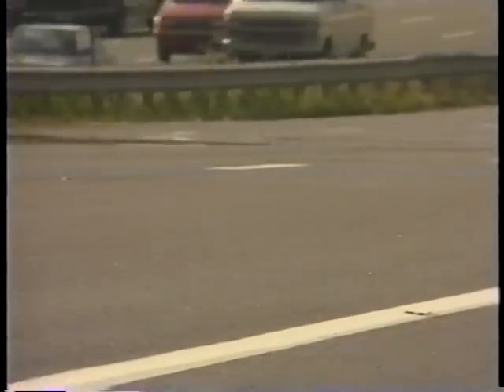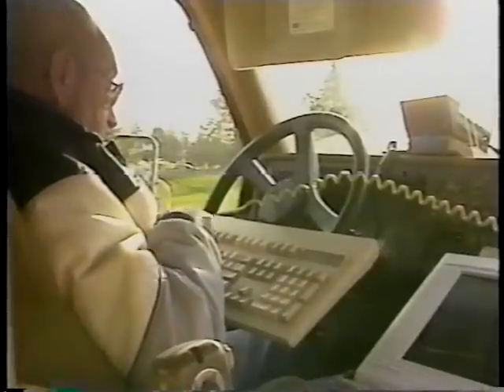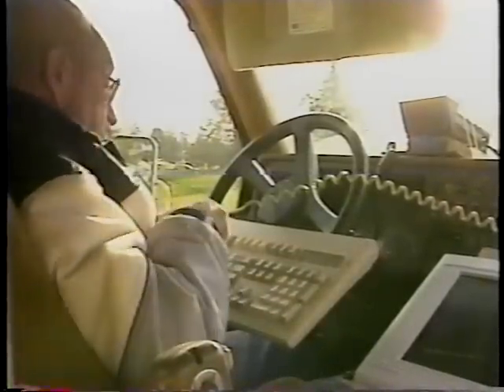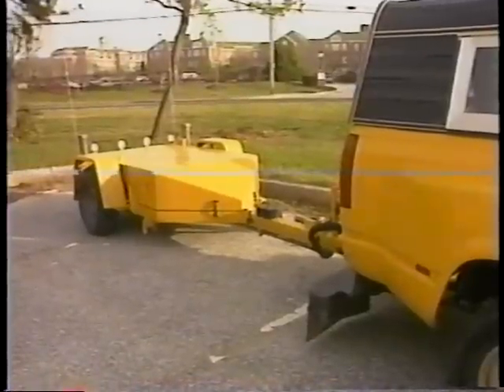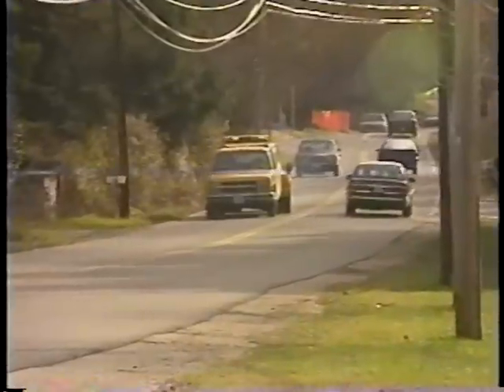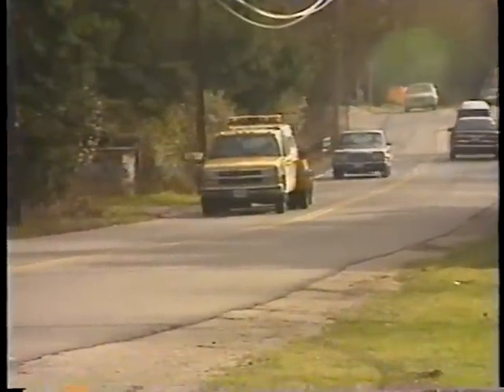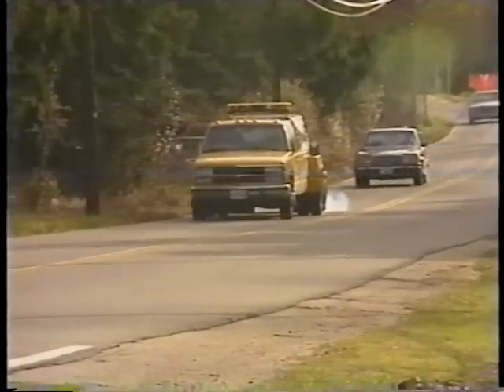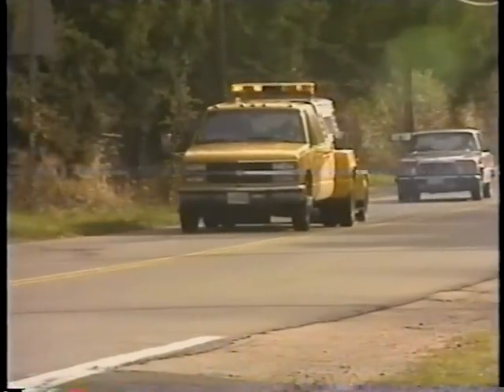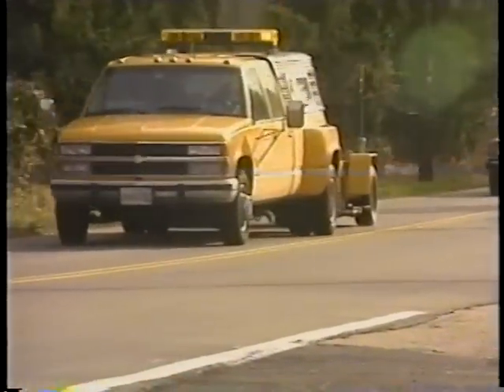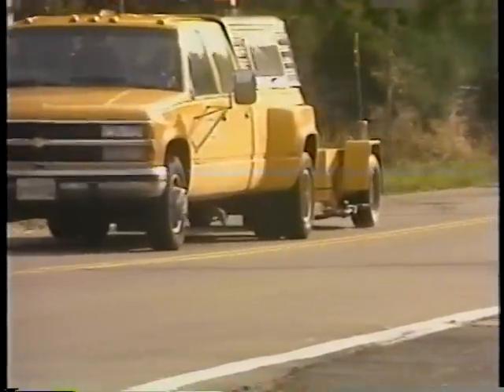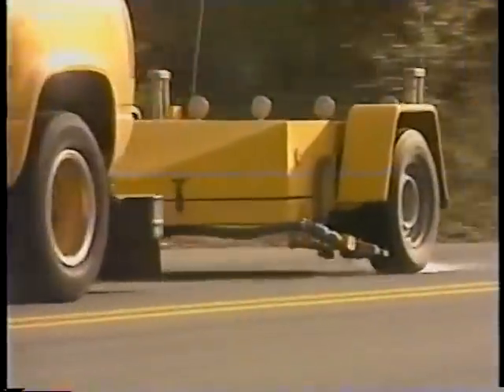They define skid resistance as the amount of friction between the road surface and the vehicle tire. In North America, engineers commonly use an ASTM locked wheel trailer or skid trailer to measure friction. It drags a locked wheel across a section of pavement and records friction values. The coefficient of friction, or mu value, is the towing force divided by wheel load. Values less than 35 are considered hazardous.